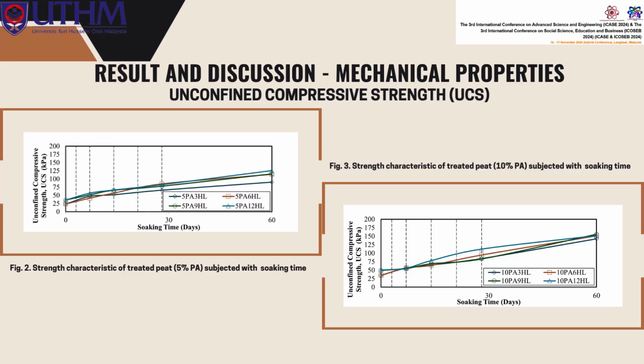Next, in Figure 2, Sample 1 shows an interesting trend in strength during soaking. Initially, there are increases of 18%, 102%, 4%, and 32% at different stages. However, at 28 days, strength drops by 43%. Despite these fluctuations, the strength reaches a maximum of 91 kilopascal after 60 days. This shows a complex interaction between pond ash content, soaking duration, and resulting strength. Analyzing these trends can provide valuable insights into the material's behavior and guide its applications in construction and other industries.